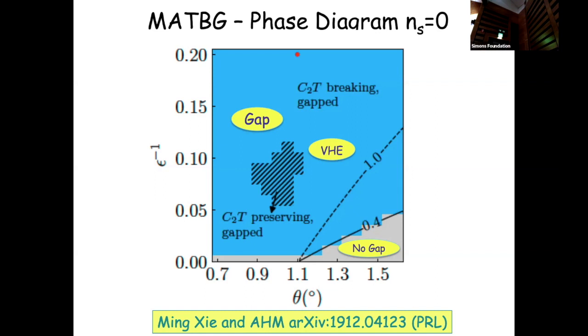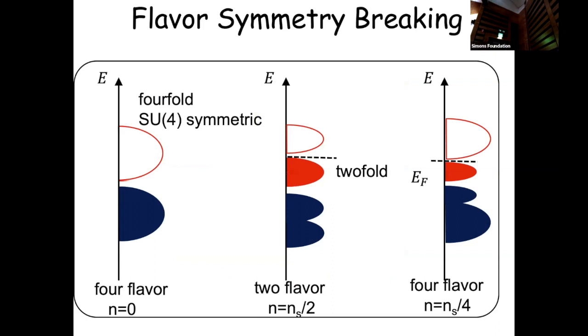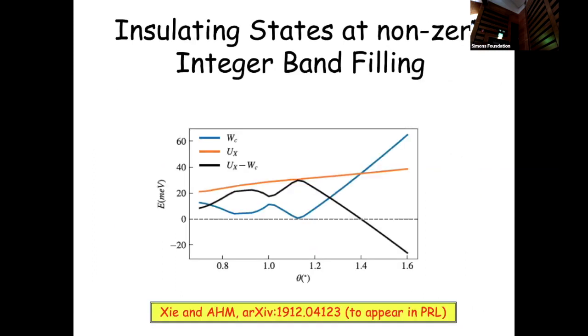It's the gap at the other integer filling factors which were really a surprise. And I think now it's quite clear that this is some kind of insulating magnetic state, analogous to an AFM state of an antiferromagnet, if you like, except that instead of having spin, you have spin and valley. It turns out the valley polarization, combined with that topological structure in the band structure, is what is responsible for the quantum anomalous Hall effect.